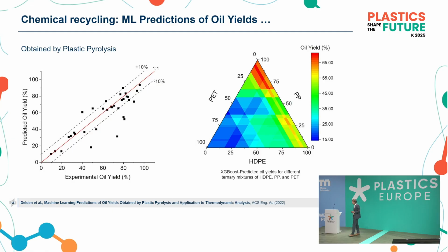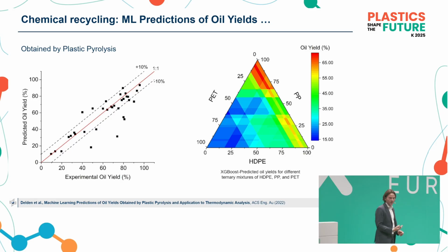And the same is true also for other compositions. So for instance, when you have PET, polypropylene, and HDPE, also typical materials for packaging. So if you want to pyrolyze these materials, it's also very good to know where you can have the maximum yield in these different compositions. So if you look to the right side, here you see a triangle of the different compositions, and the max yield you can always have if you have a very high content of polypropylene and you can afford a certain content of the PET inside the mixture.